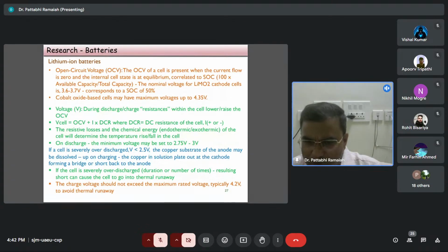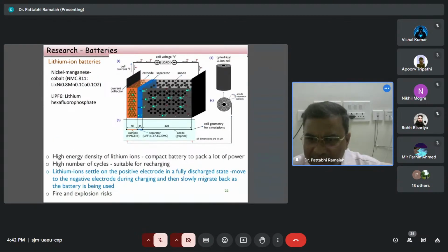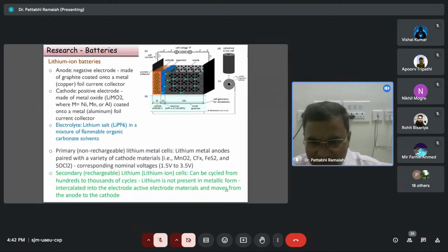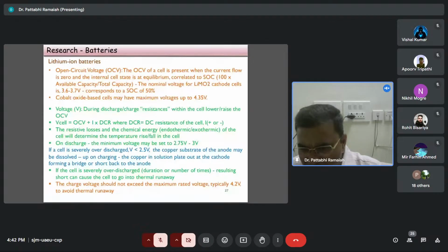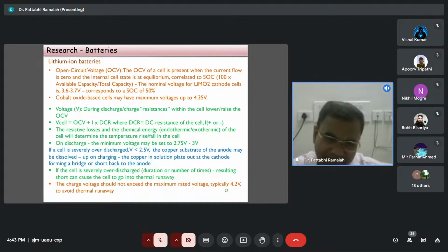for instance, the voltages are less than 2.5 volts, then the copper substrate of the anode. So if you remember, the anode is graphite, which is coated on a substrate. So the negative electrode is made of graphite coated onto a metal like copper foil. Therefore, this copper foil starts to disintegrate during extreme discharges for voltages less than 2.5, dissolving in the electrolyte, and then they will be reaching the cathode as well. And this creates a problem upon charging, because the copper in the solution plates at the cathode, they form a bridging or short circuit with the anode, which is not expected.